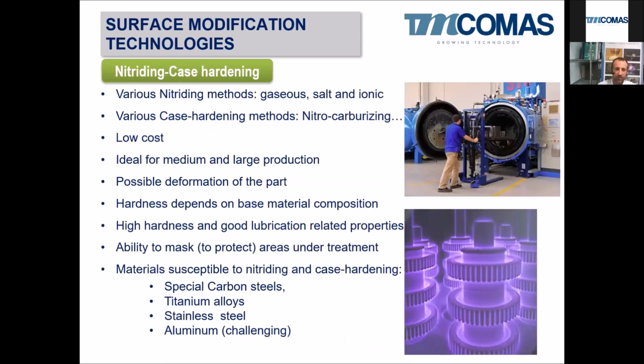Nitriding and case hardening, these surface treatments are also done in furnaces or ovens like those here. There are different nitriding methods using gas, salt, or ionic, and also carburizing. With case hardening, we have nitrocarburizing and other kinds of case hardening processes. I would say they are quite low cost processes. They are ideal for medium and large production because, depending on the size of the furnace or the oven, a lot of parts can be placed in it. There is the possible deformation of the part, since all these processes are done at 500 to 600 degrees. So depending on the size and the dimension of the parts, there can be some deformation.